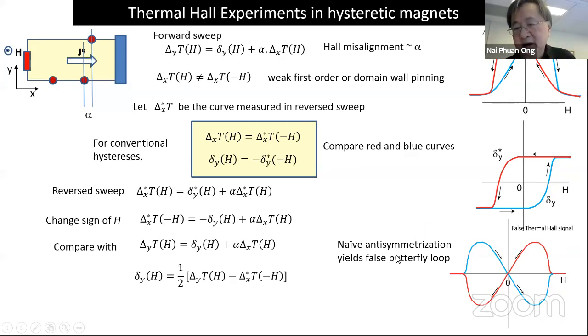Now, what if you did the naive thing, the anti-symmetrization? Here, if you assume a case where there's no Hall signal, completely zero thermal Hall signal, then all you're doing is anti-symmetrizing this curve. And I need not convince you that you will just see a beautiful butterfly hysteresis. For a long time, we were seeing these curves and not understanding why they were so distinct and unusual. Whenever you see a butterfly hysteretic curve, then you're doing something foolish.